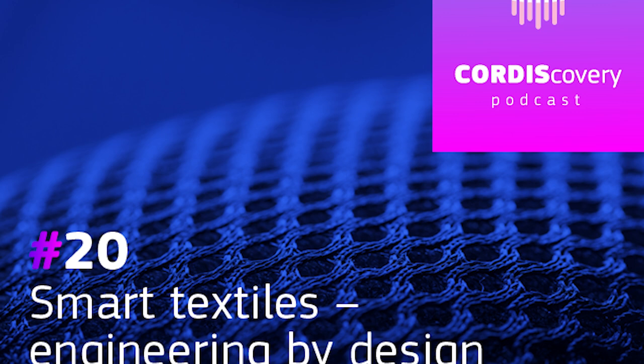Working with textiles, as I say, was more difficult because chemistry soaks into a textile, it can spread out. So we needed to try and avoid that. To some extent, we wanted it to go into the textile so that we'd get very robust and good electronic conductivity, but also we didn't want it to spread too much so that we got short circuits. So yeah, we certainly learned a lot throughout the process of using a very different type of material.